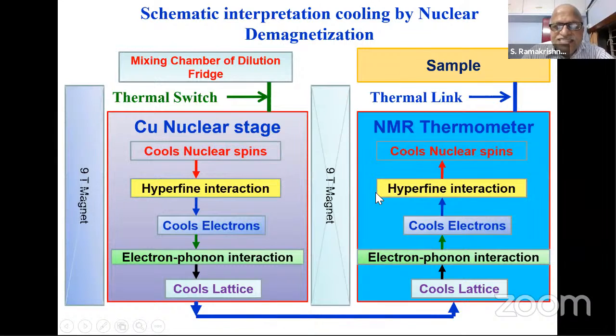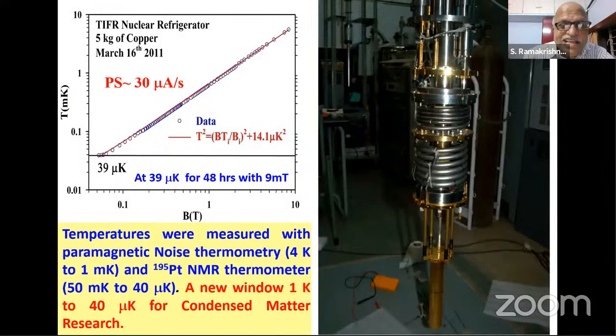As you go to lower and lower temperatures, the measurement takes a long time because the thermometer has to come to equilibrium. So at something like 100 microkelvin, you can only take two readings per day. In 24 hours, you can have two data points. When the fridge runs, we run it for 3 to 4 weeks. At higher temperatures, of course, you will have more data points. But at the lowest temperature, because of thermal relaxation, everything has to come to the equilibrium temperature, so you need to wait for a long time. So the experiments are not for the faint-hearted. What we showed was that we can cool the system down to 40 microkelvin. The important thing is that we can keep this temperature for more than 48 hours for experiments.